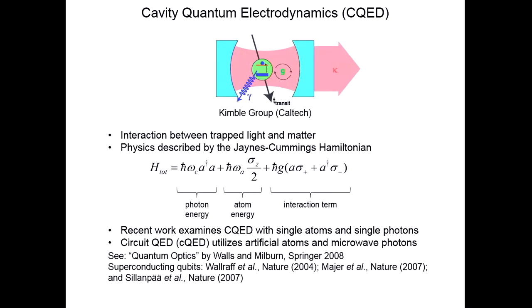Where if I start with the atom in the excited state, it can transfer that excitation and create a photon in the cavity. At a later time, the photon drives a transition from the ground state to the excited state, and you just move this excitation back and forth between the cavity and the atom as time evolves, right? Now, this is described by what's called the Jaynes-Cummings Hamiltonian. It's shown here. Here's a term that looks like h bar omega a dagger a. That's the energy of the photon in the cavity. And generally, you'll have a 2-level system that has some transition energy. This term here just describes the energy of that 2-level atom, depending on whether it's in the ground state or the excited state. And this is the interesting interaction term or hot potato term that describes how this excitation is transferred back and forth between the atom and the cavity as a function of time.